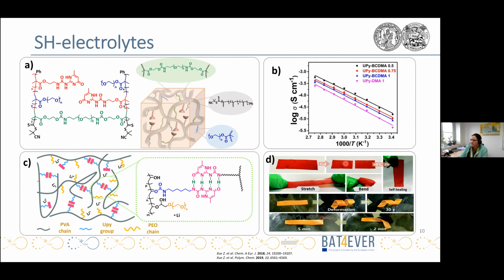After cutting, as you can see here, this film can successfully be self-healed after 2 hours at 60 degrees. And then at 60 degrees, we can change the form of the polymer film, for example, by rolling. And then when it's frozen in liquid nitrogen, we can obtain a spiral-like shape. And then when heating it again, this temporary shape is lost again, and we have our initial shape of the film.